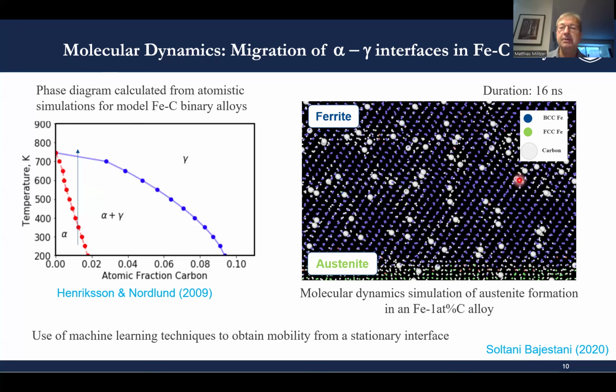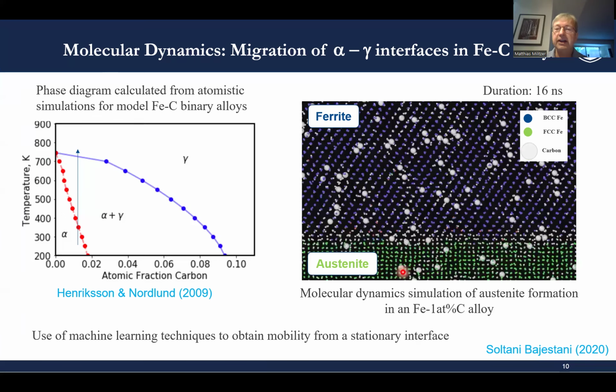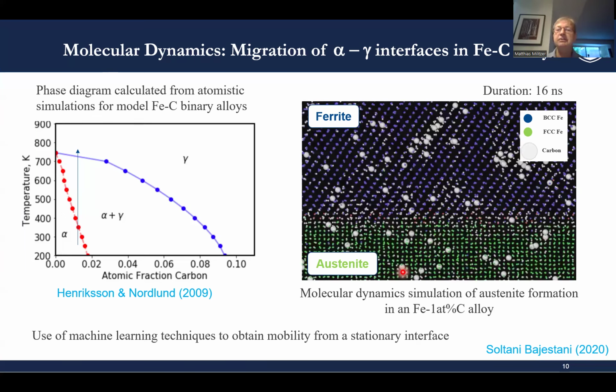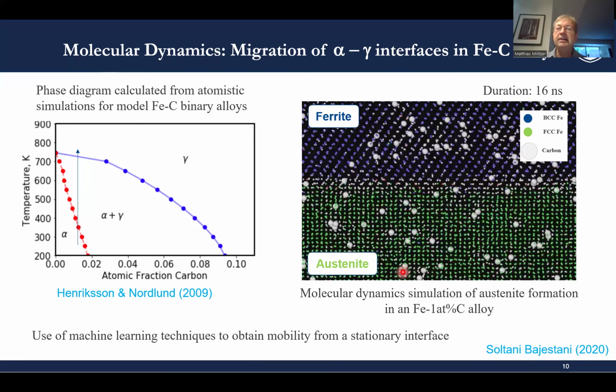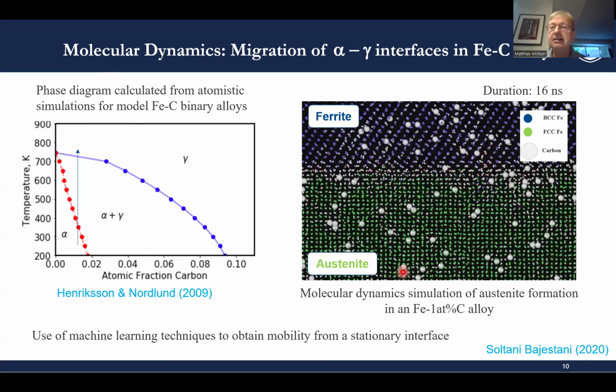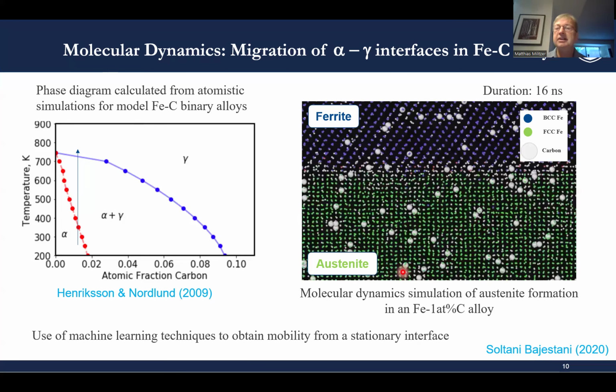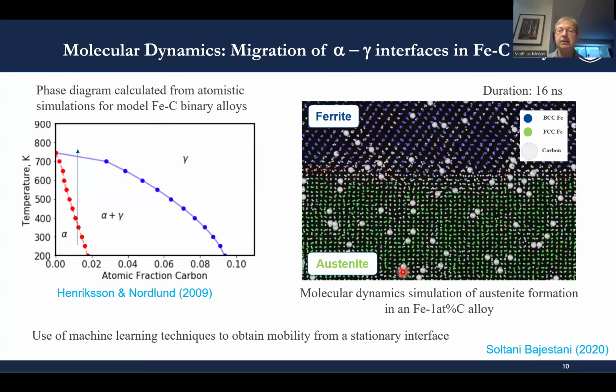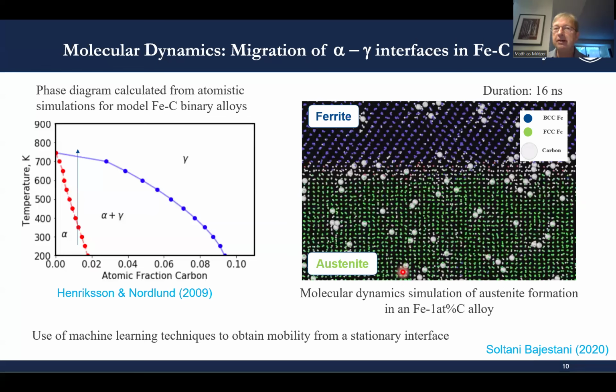We can heat up our specimen that is shown here with an austenite film at the bottom and ferrite on the top in blue. The large white dots represent carbon atoms. So we go into the austenite phase field. And what we see is that the austenite grows and consumes ferrite. Initially, the interface moves very quickly. And then it seems to come to a bit of a standstill. But we see also that we get an increased enrichment of carbon at the interface. And the atoms still jump around at the apparently stationary interface.